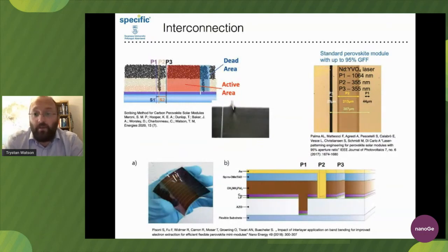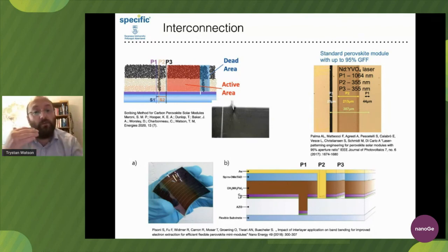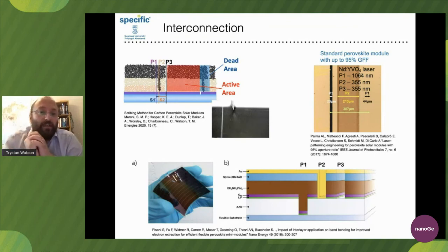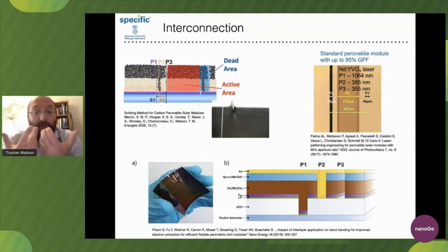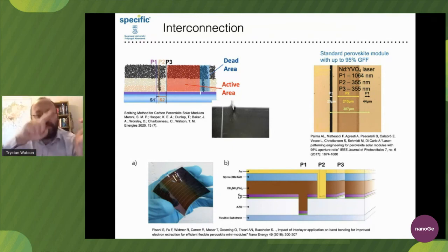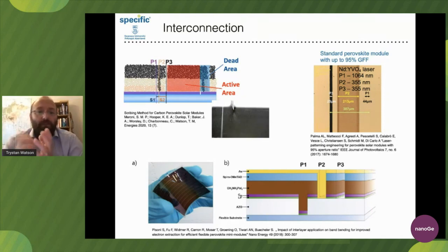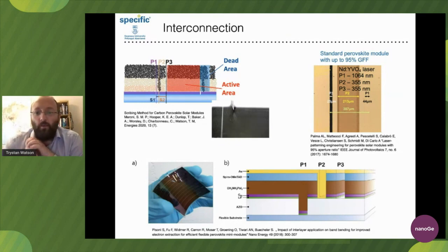For interconnection, which we'll see in Aldo's talk: to produce a series-connected device, you need to overlap one electrode with the other, and you have to remove material - either using a laser or a mechanical scribe - to allow that. You make subsequent depositions and then one electrode sits over the underlying electrode, achieving the pathway needed in a standard series-connected module. How perovskite responds to interconnections varies significantly depending on what material you use, which is why we have the great work we'll hear today.